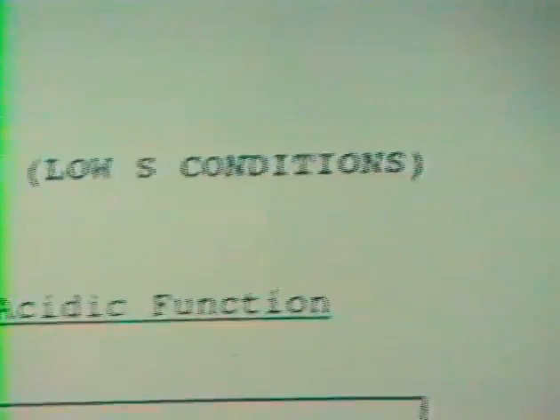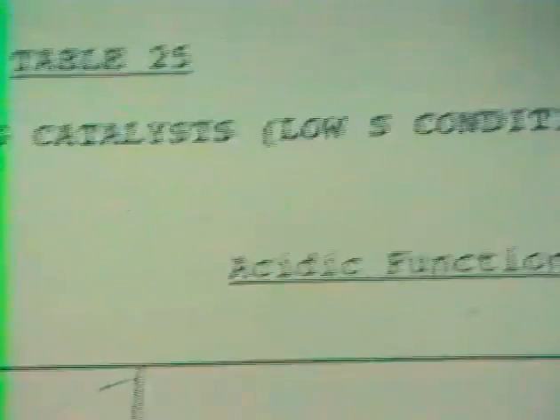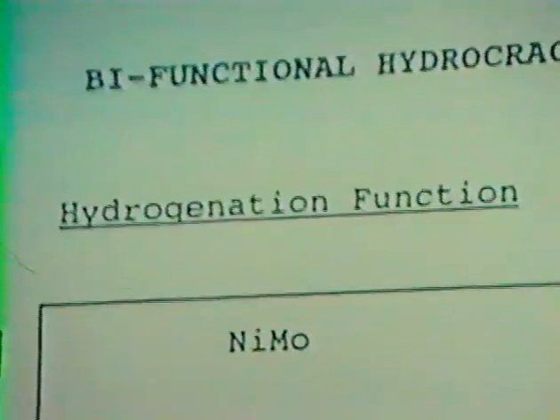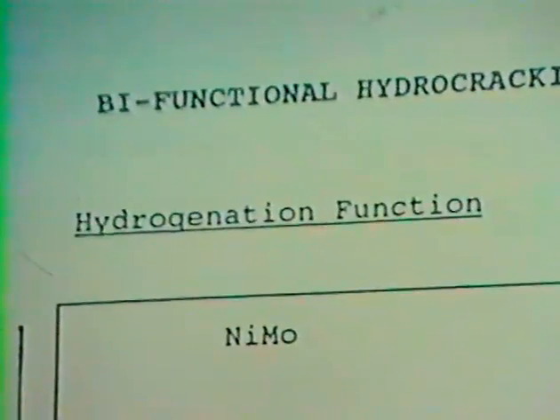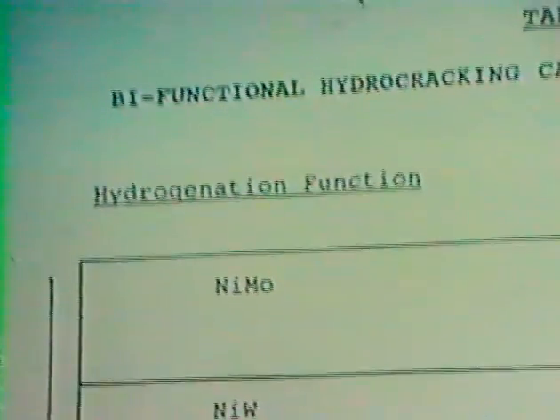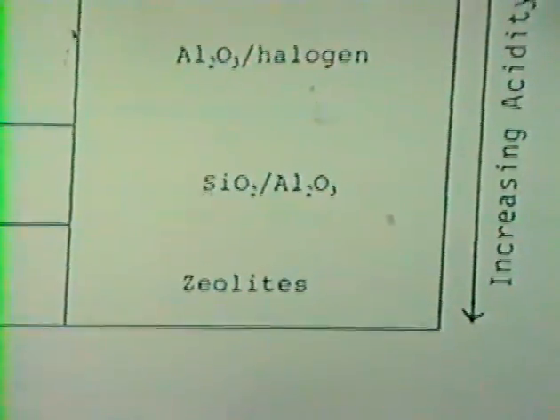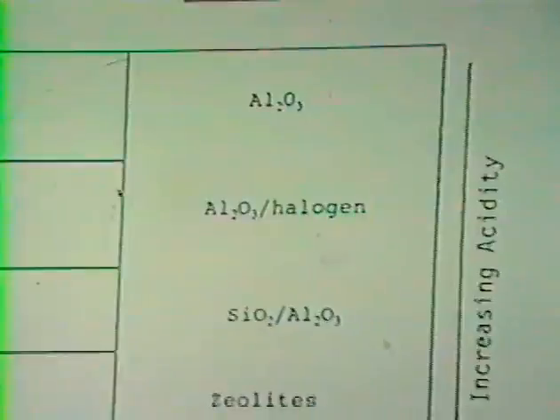Look in the literature, the amount of information on the hydrogenation component and the cracking component in hydrocracking catalysts is very slim. This about summarizes it. Increasing the hydrogenation power, you go from nickel molybdenum to nickel tungsten to platinum palladium. And for the acidic function, you go from alumina to fluoride alumina, silica alumina, and zeolites.